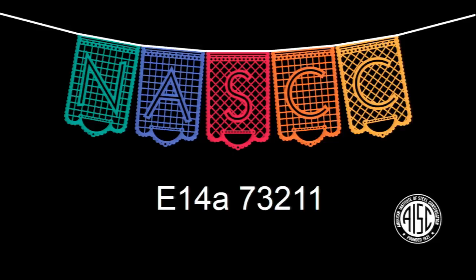We're working with the Army on very high-strength steel, where you're normally using a 50 KSI material. We're actually making a steel casting with 180 KSI material, so it's got really limited ductility. But we're using some funky heat treatments now to try and get that grain refinement and get the performance up. So the mechanical properties that you need are available in steel castings. I don't know of any requirement that you might have that we wouldn't be able to make. We can make things higher than 180 yield, but then we begin to lose ductility and toughness. So we make the grinding media that people use. We make castings with 500 or 700 Brinell, so they're up around 300 KSI ultimate. They don't have any yield. They just break.